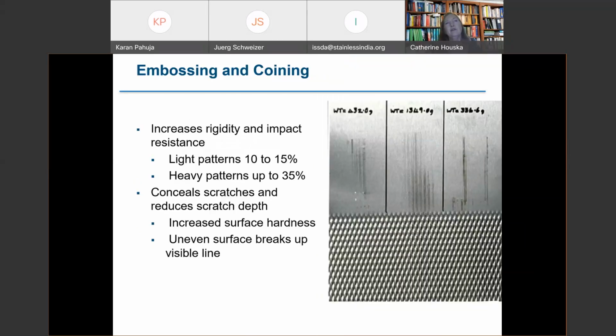The light patterns will increase the rigidity and impact resistance by 10 or 15%, while the heavier patterns up to as much as 35%. If you're concerned about impact resistance, for example, column covers at an airport or some other high traffic facility, then a heavier pattern should be something to be considered, because that could allow you to use a thinner piece of stainless steel while still getting the impact resistance that's needed.